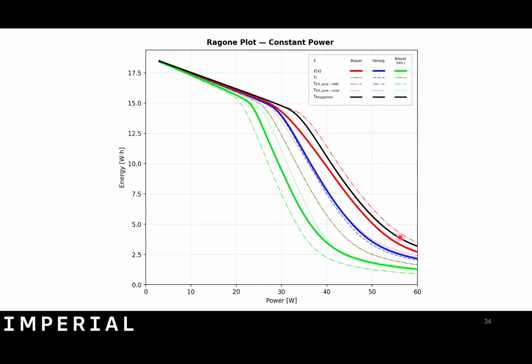And here you can see the impact that this has on performance. And this is a sort of Ragone plot showing the available accessible energy as a function of power for a cell. And you can see that the different systems, so the bilayer and the bilayer reverse, have very different accessible energy. So you look at the thick lines, the homogeneous cell, so the cell made uniformly, it's got about 40 watts, it's got about 7 watt hours. But if the bilayer is made badly, i.e. the wrong way around, you halve that. And if it's made well, you can add about 40%. So it's a really exciting result.